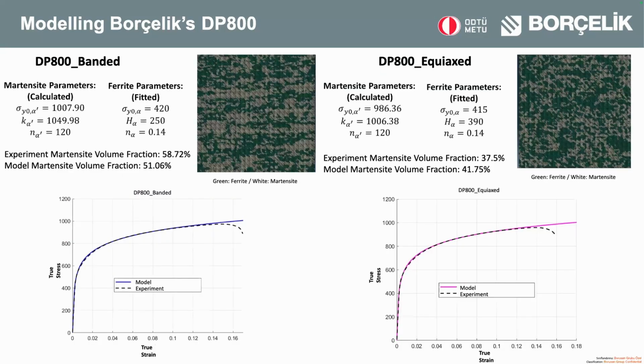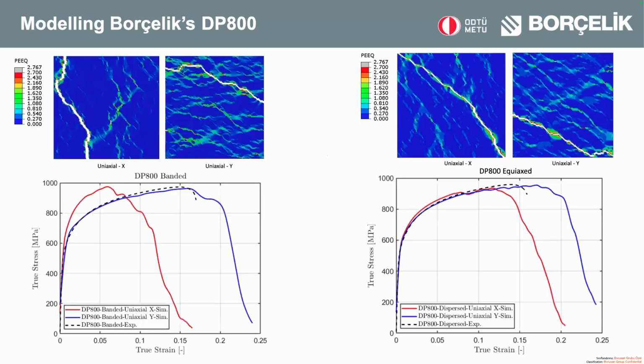So these are the data we used during the curve fitting operation. We did this separately for the banded structure and the equiaxed structure. We fit the model very well for these two cases. And then we did fracture analysis using the flow curves we achieved previously. To do the fracture analysis, we use the element deletion method, and we give some set of parameters for ferrite and martensite separately.